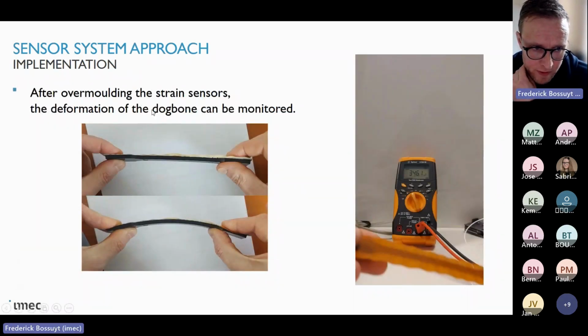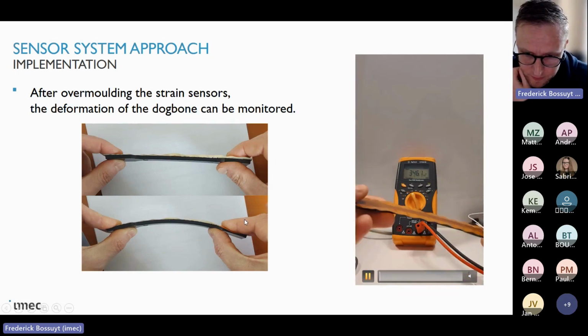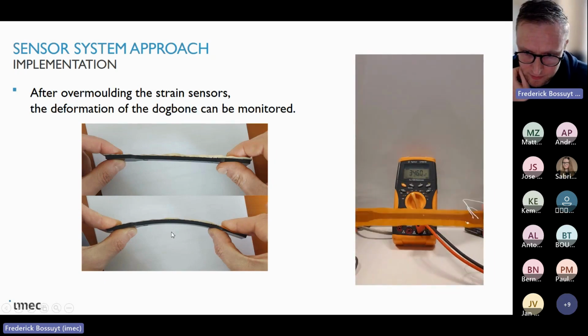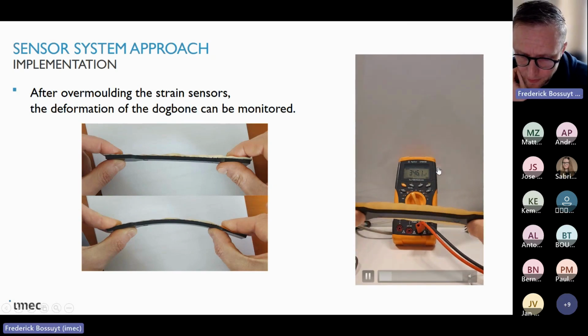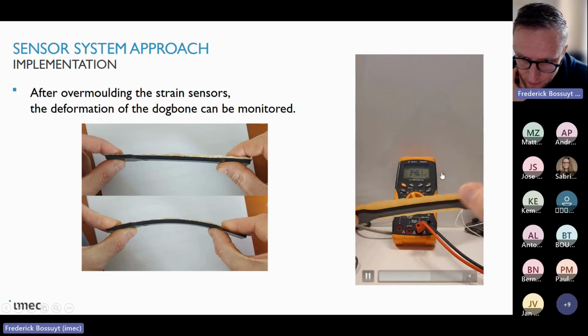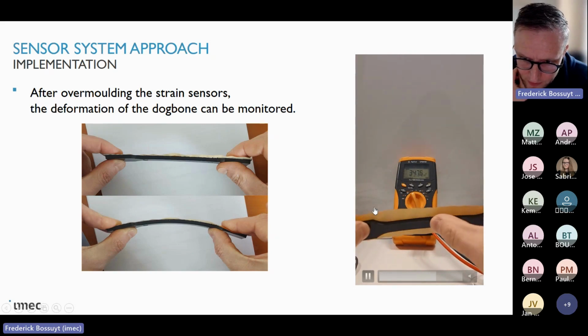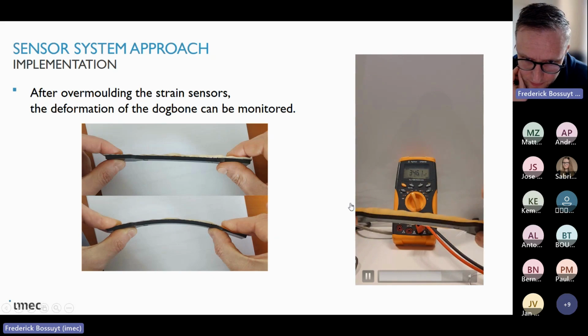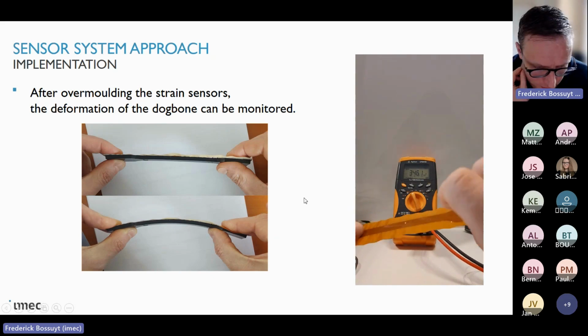And then here you see a quick demonstration of the sensing capabilities. This is the dog bone with the sensing foil. There are 5 strain gauges on it, but we only measure 1 here. And during the bending of the device, we're able to capture the local strain. So it's in ohms, which needs to be translated into the strain. But as you can see, the feasibility has been demonstrated.